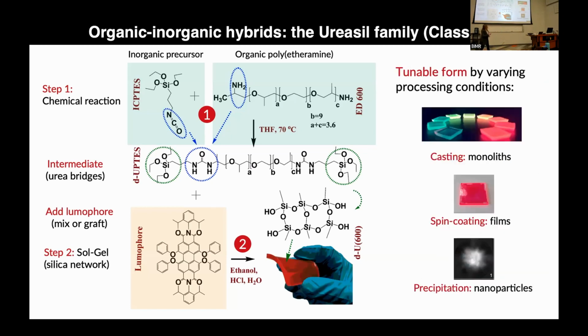This mechanical tunability means then that we can also vary the processing conditions. And so we can obtain samples by casting in a mold and obtain freestanding monoliths. We could cast our materials on a substrate and obtain a film, or we can even precipitate our ureasils as nanoparticles into a dispersion medium. So you have different ways of processing the ureasils in order to develop our photon conversion system.